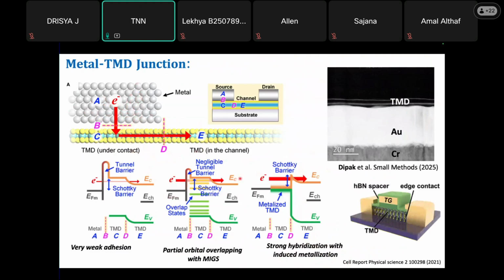How do you achieve that? The top layer coating, if you have a monolayer coating a metal on top of it, as I showed here or here, will not work because there will be a physical gap. So you need to deposit from the side. The metal needs to be deposited from the side.